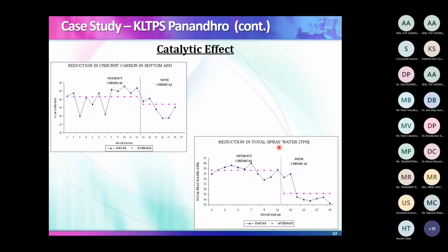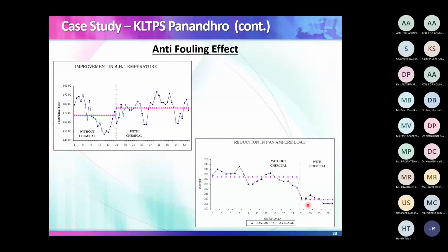Similarly, anti-fouling. How will you judge anti-fouling? If there is an improvement in the temperature of steam, that is a positive result because your tube has become cleaner, so heat transfer has become much faster. So here, without chemical, it was about 467, and with chemical it goes up to 475. That is the improvement in steam temperature. Similarly, if the resistance in the system reduces, your power has to reduce. So anti-fouling effects should give me a result in terms of power reduction in fans. Here is the fan power in amperes. Without it, it was about 234, and with it, it has come down to about 207 amperes. So it has an anti-fouling effect.